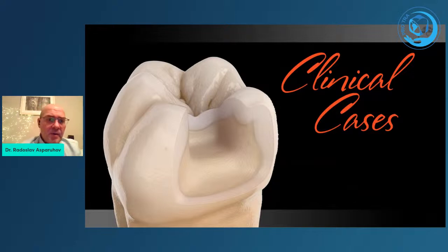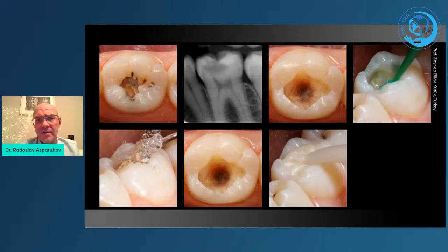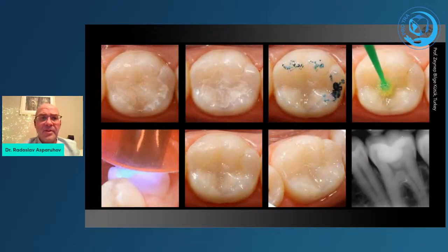complaints from the patient. I will show you a couple of cases, not for any other reason, but to show you the difference, especially with the aesthetic point of view, because I will speak very, very shortly also about the longevity of the restorations. Those are clinical cases of Professor Kütük from Turkey, and she has very nicely documented cases like this one, with incomplete partial caries removal, after using the cavity conditioner, rinsing, and then placing the glass hybrid in bulk. It was waited till it became dull, then it was adjusted occlusally, checked with articulating paper, then applied the resin coating, which is afterwards light cured. And you can see the aesthetic result on the last two pictures.